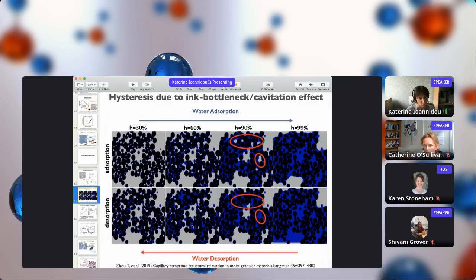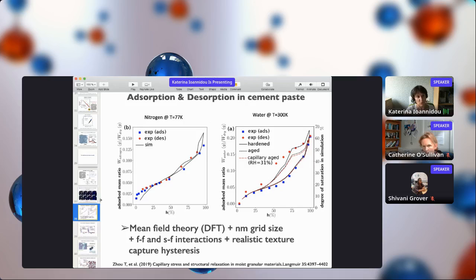Then we have also the desorption, and we can see that at the same relative humidity, the material is adsorbing and desorbing water differently. This is something that we can also observe when we plot what we just saw, plotting the adsorbed mass ratio against the relative humidity. For nitrogen at 77 K, which is the temperature usually where the experiments are performed, and for water at room temperature, we have an adsorption and desorption that has the same path for nitrogen, but for water we have a hysteresis loop, which is what we just saw before. So basically, with this simple mean field DFT theory, we are able to capture such a complicated phenomenon of hysteresis.